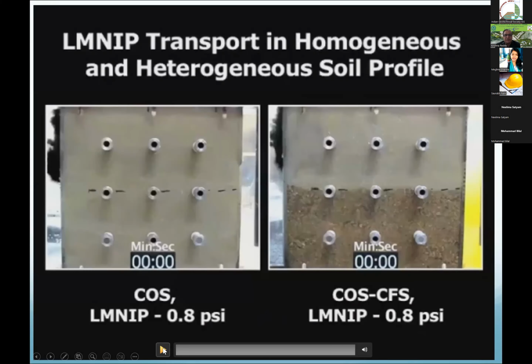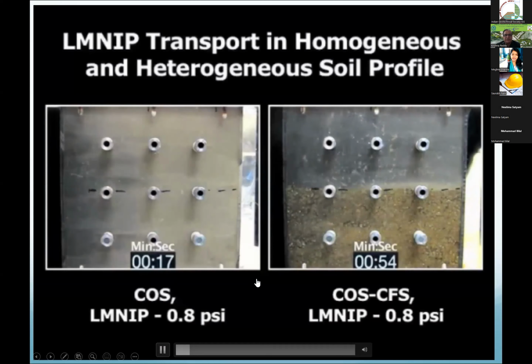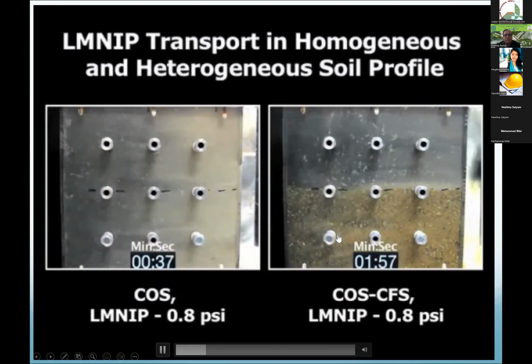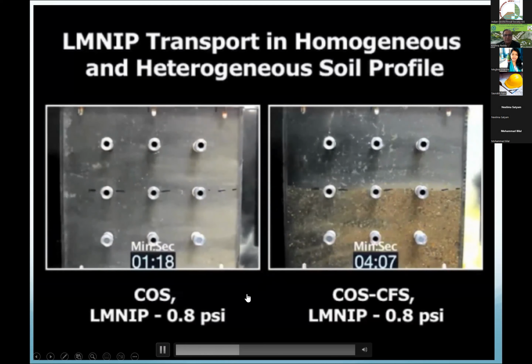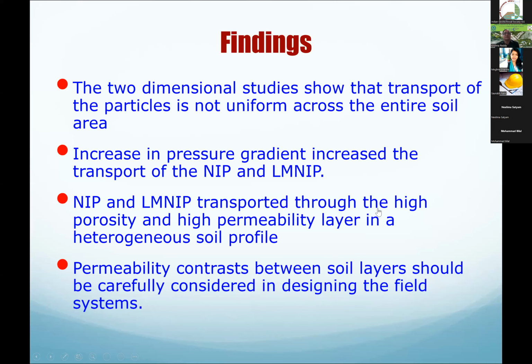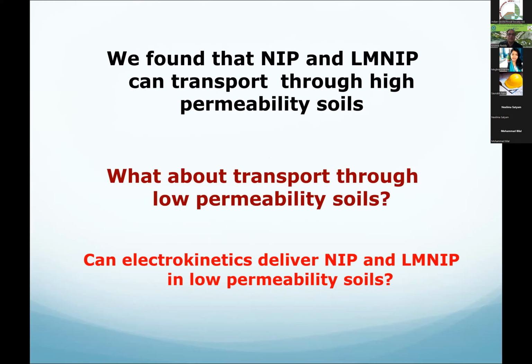And here, again, the different layers in heterogeneity is going to be a huge problem. So you're going to get this transport through the high permeable zone, not so much from the other. So this is a uniform one. If you have a uniform one, it goes through the entire thing, whereas here it does not. So basically the whole idea is, lactate modified nanoiron particles can really help transport through the sands, irrespective of type of sand. But if you have layered profiles, it's going to transport through high permeable zones.